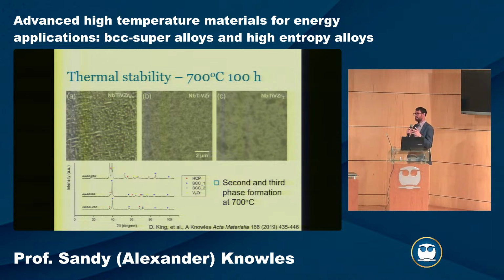So for things like cementite, it's a question of whether you can have slip transfer from the matrix to the precipitate, but also the length scale. If you make it very, very fine, as with cementite in pearlite, you can get good ductility because you make it small enough that you can still force dislocations through it. So there are things you can do on microstructure, and other things you can do on the fundamental design of the deformation in that intermetallic. In general, we've stuck to these ordered BCC systems because we think we can get better load transfer and dislocation slip from the matrix into the precipitate. Whereas with a Laves phase, or maybe cementite, if you have a large carbide, it's more likely to be brittle.